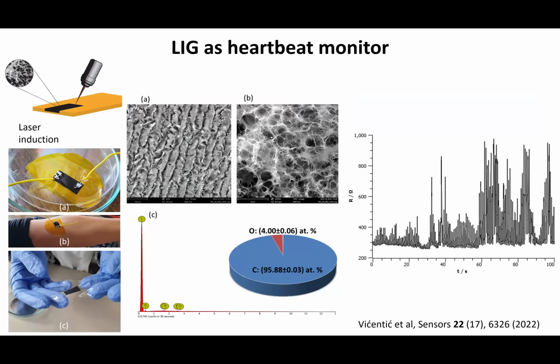We set out to play with this material a few years ago as well, and we also started from Kapton, which we irradiate with the carbon dioxide laser, and then what you get is shown here in the middle. These are scanning electron micrograph images, and right in the center, part B is the classical SEM image of laser-induced graphene. You see that it's mostly a porous, foam-like structure with walls made of few layer graphene. That's, I guess, the definition of LIG.